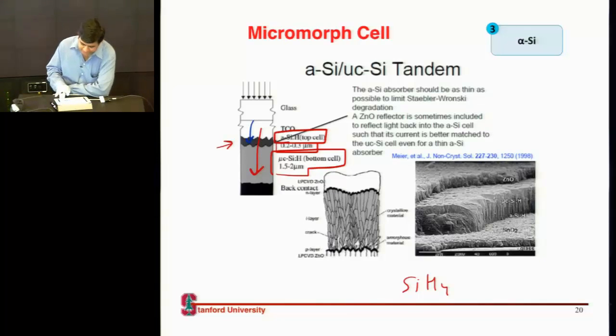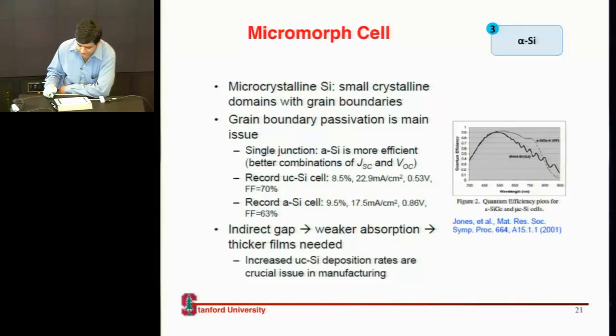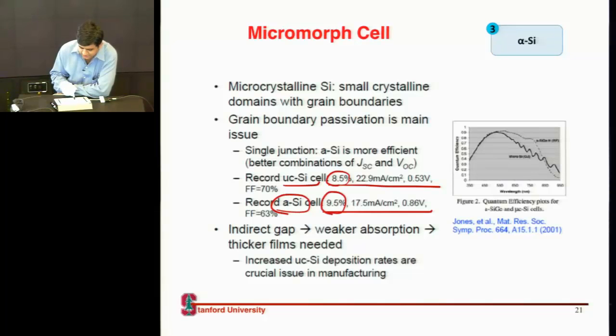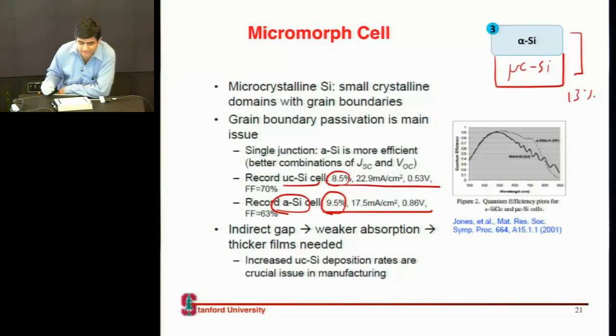So that is essentially a big task, and it adds a lot to your processing cost. But in fact, people were able to get decent efficiency. So if you just look at a microcrystalline cell, its efficiency maxes out at 8.5%. Amorphous silicon, the efficiency again maxes out at 9.5%. For a tandem, using amorphous silicon at the top and then microcrystalline silicon at the bottom, at least in lab, people have shown efficiencies of around 13%.